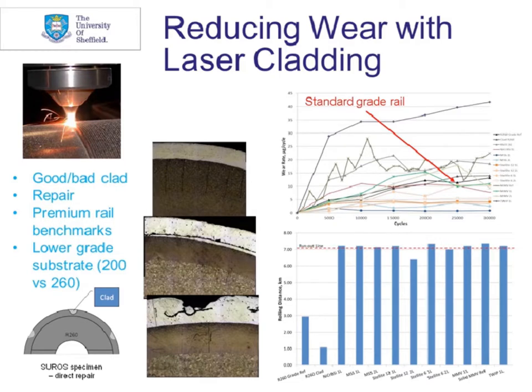As you can see from the pictures, we've looked closely at what happens when you have a good clad, but also what happens when you have a bad clad. Obviously, the railway industry is very safety critical. We need to understand what might happen if a poor clad layer happened to be imposed. The way we're looking at using this is that we would apply this to quite high value track components. Most of those would typically be removed for refurbishment, but the idea of in situ repair is interesting.